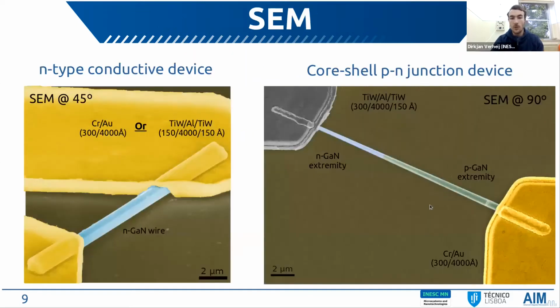And so here I show you what the devices look like in real life. So we have on the left side the N-type conductive device using the N-type gallium nitride wires. And in this case, we have samples with both chromium gold contacts or with titanium tungsten aluminum titanium tungsten contacts. And these contacts usually give us ohmic contacts, while these create nonlinear contacts. And here at the right side, we have a p-n junction diode device. And if we look here at the p gallium nitride extremity, we can actually see that the diameter of the wire is slightly larger, which is exactly because of the additional p gallium nitride shell.